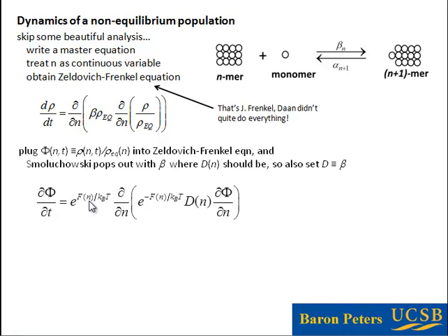It's a function of nucleus size, this free energy, and we also have a mobility, and that's our diffusion constant. Okay, so the diffusion constant in principle, in general, can depend on nucleus size, and we usually expect, in fact, that the rate at which you add monomers is proportional to the surface area of your nucleus. That is a quite common model for this. So we do expect this diffusivity to be a coordinate-dependent diffusivity.